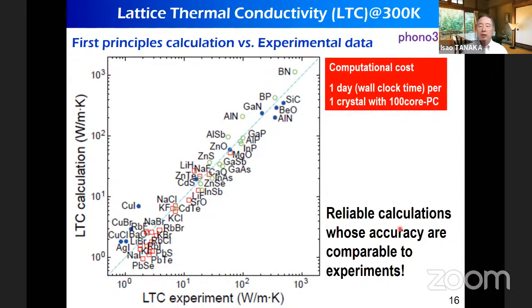As I mentioned, this is a very time-consuming calculation, and we have to handle a lot of DFT results. So the computational cost is 1 day for one particular crystal using a 100-core PC. So if you want to compute exhaustively all 55,000 crystals using this PC cluster, then you need 100 years. So you can find it prohibitively expensive to obtain all the data. Not impossible, but very difficult.